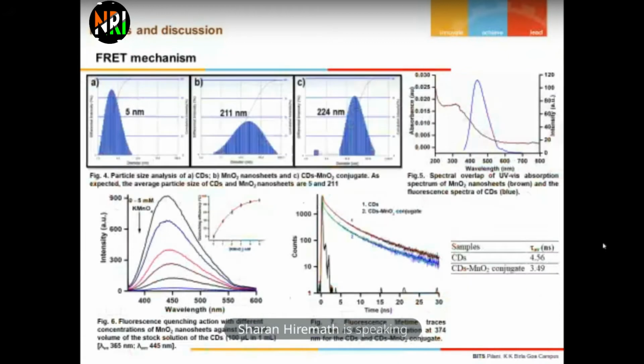Now coming on to the FRET. Again, the DLS shows 5 nanometers for CDs and 211 nanometers for MnO2 nanosheets, and upon combination of CDs and MnO2 we can see two peaks here. One is a very small peak which is around 5 to 6 nanometers, and there is a huge peak at 224 nanometers. It shows that the CDs are not only on the surface of the MnO2, there are also a few carbon dots which are free in the solution.